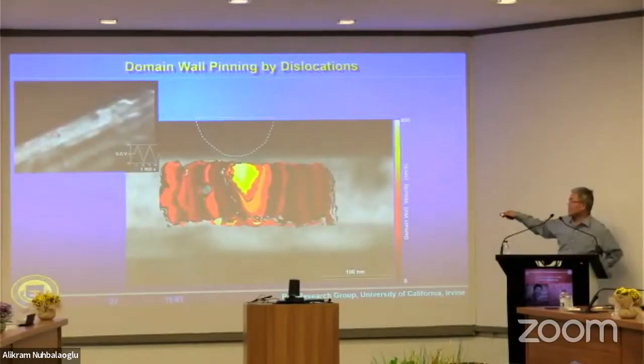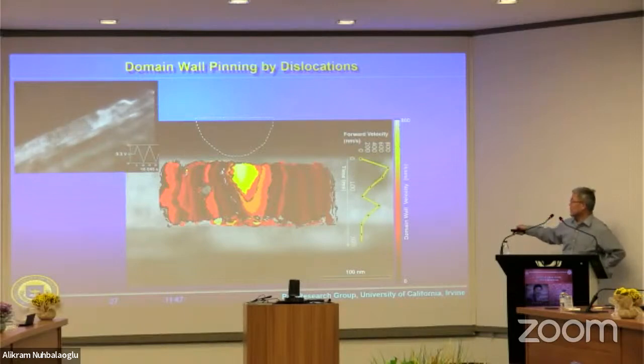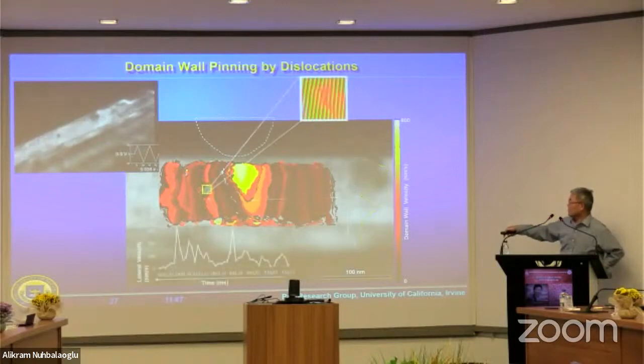So this is the dislocation. The domain nucleated, and the domain wall moved to here. You can see it slows down a little here, but we need to analyze to get information. So then you can track how the domain moves in the vertical direction, that is the velocity measured here, or the domain wall motion along the horizontal direction, the velocity is tracked here. You can see that the domain wall motion is getting slower and slower because it's moving away from the strong field region, and then slows down. And then eventually it is almost not moving for a while. And then suddenly it becomes very high speed again.